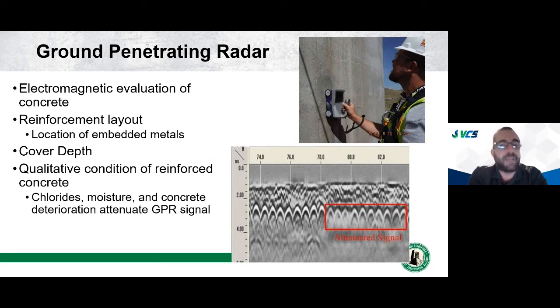GPR will be affected, so that signal will be weakened if there is a delamination above this area. However, if there's just moisture and chlorides in the concrete, that will also weaken the signal. So I can't tell the difference in the signal between a delamination, some just micro cracking, some corrosion, or just some moisture. So GPR tells you where to look further, but it is not able to discern different types of damage. So if anyone is expecting GPR to tell them where delaminations are, they're being set up for failure, because yes, it will be affected, but you will not be able to identify, yes, that's a delamination, or no, that's not.